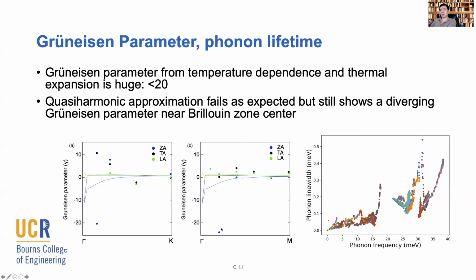And this big disagreement between this measured data point versus our calculation shows that this is a very strongly anharmonic phonon mode. And that's kind of expected, since all those flexure modes are weakly bonded and their mode potentials have a large higher-order force component compared to their harmonic part.